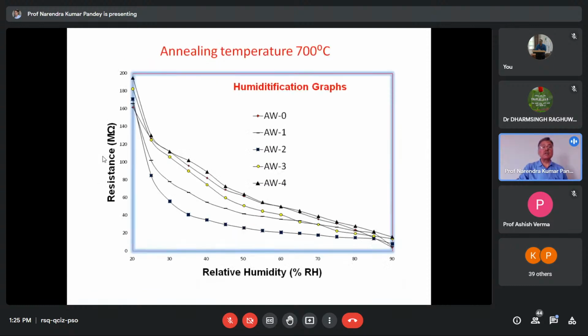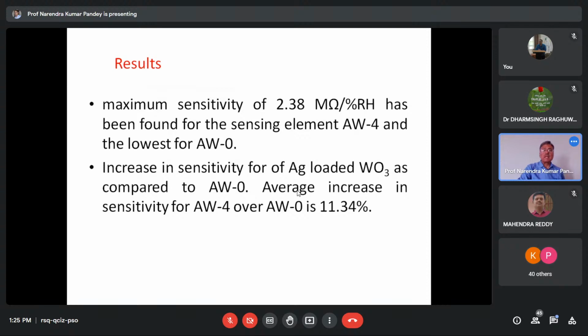So for 700 degrees centigrade, you can see the trend. Resistance versus relative humidity. This is for pure WO3. This is for 1% Ag in WO3, 2% Ag in WO3, 3% Ag in WO3, 4% Ag in WO3. What do we find? Maximum sensitivity of 2.38 megohm per percentage RH has been found for the sensing element with 4% Ag. When you add 4%, then maximum sensitivity is this much. And from 0% of Ag in WO3 to 4% of Ag in WO3, the increase in sensitivity is by 11.34%.